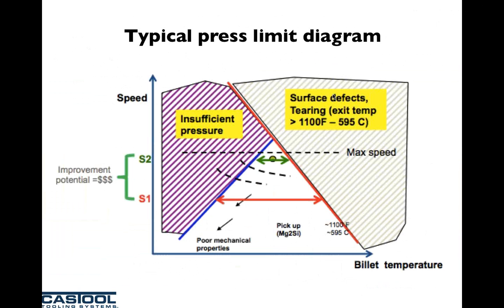So typically what people are trying to aim for when they look at their press limit diagram is, you can see at the bottom, the billet temperature. And people try to narrow the billet temperature so they can improve the extrusion speed. So they bump it from red to the green, so they increase their profits. When you take a look at the red line here, if you had control of your billet temperature of maybe plus or minus 20 degrees F or maybe 30 degrees even, because you have instability in your billet temperature, it doesn't enable you to hit the maximum or the peak in this triangle.